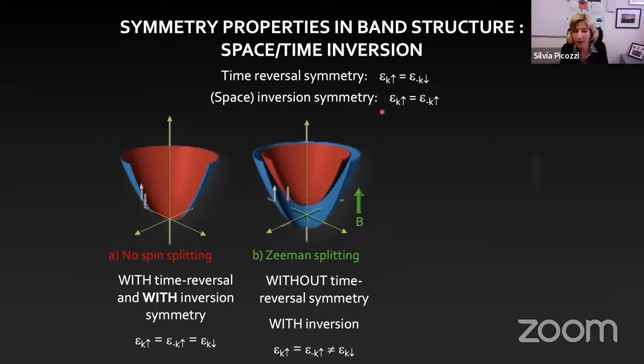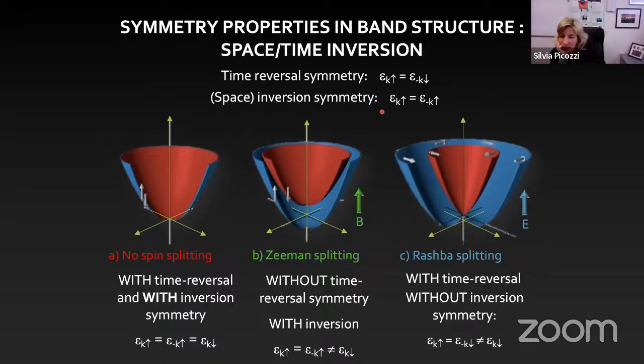If I break time reversal symmetry, so if I apply a magnetic field or if my system shows a spontaneous magnetic ordering, and if I keep inversion symmetry, then my band structure will be split, right? This is what we usually expect for a magnetic system: a band structure which is split for spin up and spin down. However, if I have time reversal symmetry, so there's no long range magnetic order, but I break inversion symmetry, then because of this relation, I can still have a spin splitting which is k-dependent, as shown here. Of course, if I integrate over all the Brillouin zone, there will not be any spin splitting, but locally, k by k, there can be a spin splitting in the band structure.